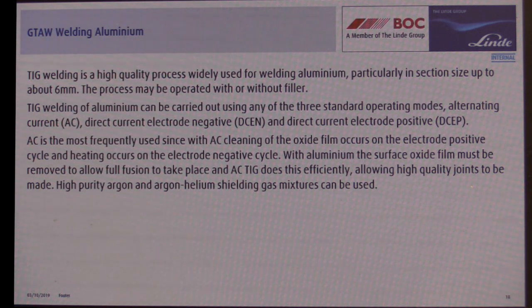TIG welding of aluminium can be carried out using 3 standard types of operation, depending on the current: AC, direct current electrode negative, and direct current electrode positive. AC is the most frequently used for removing that oxide film. It's the electrode positive cycle that does the cleaning, and the heating occurs in the electrode negative cycle. So alternating current breaks that oxide layer down, as well as the cleaning effect that you've already produced. So both TIG and MIG, you need to clean it before any operation of welding.